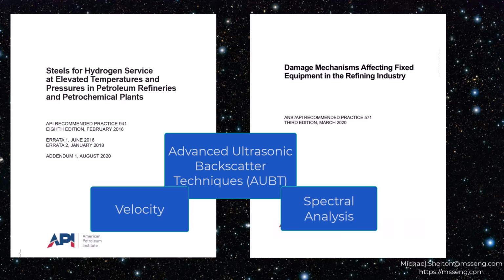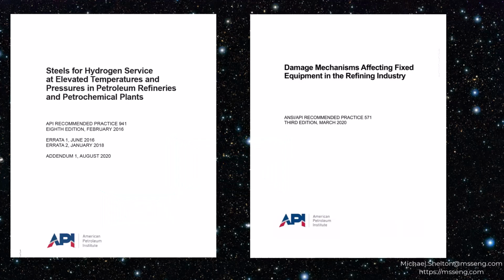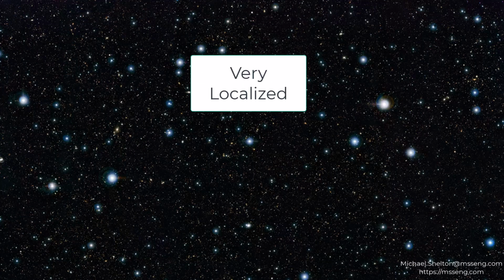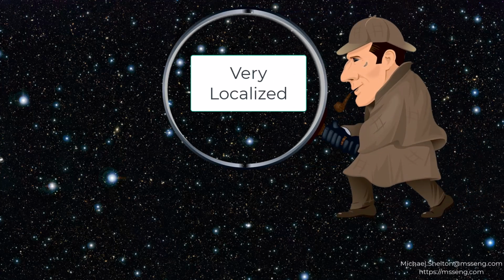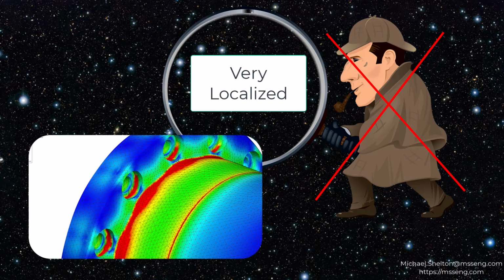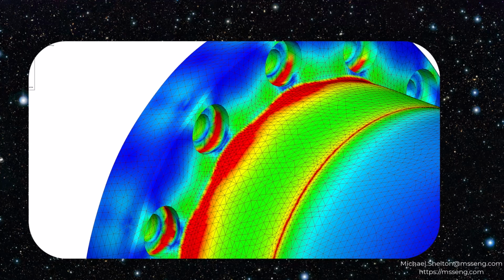The real issue with HTHA inspection, which again is AUBT now, is that it is very localized. No global inspection technique yet exists for HTHA inspection. HTHA is also a function of the stress state of the metal exposed to the high temperature hydrogen attack. Thus, it is very important to identify the high stress areas when determining the optimum locations for the localized AUBT inspection points.